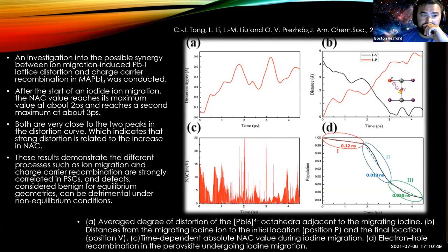And so investigations were carried out into the possible synergy between ion migration induced lead iodide lattice distortion and charge carrier recombination. It was conducted in methylammonium lead iodide. And you can see after the start of an iodide ion migration, the non-adiabatic coupling value reaches its maximum value at about 2 picoseconds and reaches a second maximum at about 3 picoseconds. And those are both very close to the two peaks in the distortion curve, which indicates that strong distortion in the system is related to the increase in non-adiabatic coupling, which helps explain some of these anomalous behaviors of perovskite solar cells.